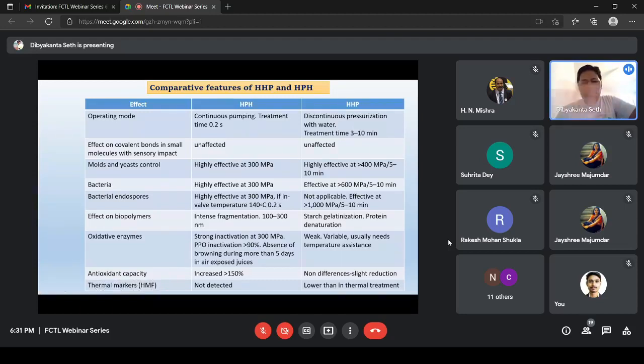So I'll give a complete overview of the things happening, or that we can manipulate, with high pressure homogenization, which cannot be achieved by high pressure processing. Like operating mode, as you know, is continuous pumping, and treatment time is 0.2 seconds, even less than that. The treatment time in high pressure processing is 3 to 10 minutes. The effect on covalent bonds in small molecules, the sensory impact, in high pressure homogenization is unaffected.